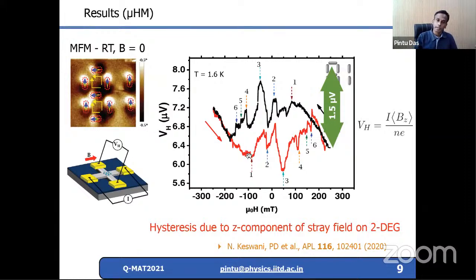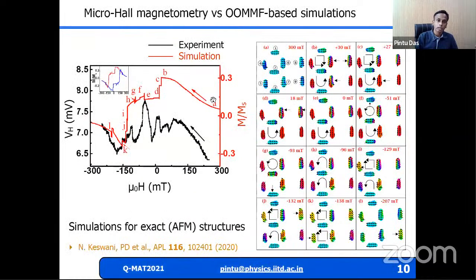Now, to understand that, because we are not averaging the signal, it is straightforward to compare them with theoretical modeling. So we have performed micromagnetic simulations using OOMMF. On the left, the black is the experimental result, and red is the simulation result, where you see that the simulation is almost perfectly matching. Features are almost perfectly matching with the experimental data, and these features show the single domain character which we observed in the MFM. We really don't see a bistable kind of state. We see in between multiple other complicated states, for example, in some cases vortex states. And all these are picked up by our highly sensitive Hall device.